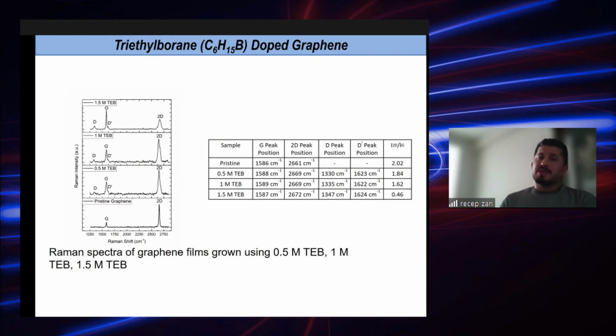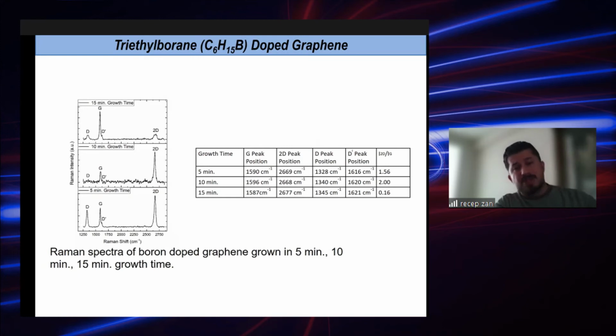The other source we used was triethyl borane, which, as I said, is used as a carbon and boron source together. This is in liquid form, and we tried to adjust the molarity using hexane. We started with 0.5 molar, 1 molar and 1.5 molar. For comparison in terms of Raman spectroscopy, we added pristine graphene Raman spectra here as well. We were much happier to see that 0.5 molar is much more homogeneous and much thinner than the other films, and much closer in terms of spectra to the pristine one. Again, after that, we adjusted the growth time, and the 10-minute growth time was the best for us.